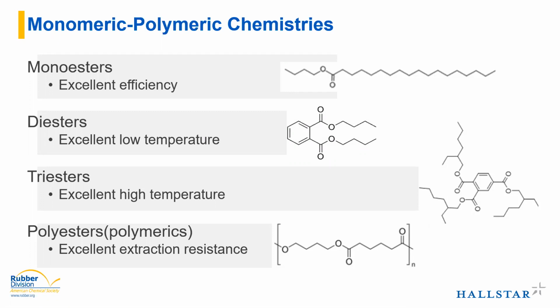Triesters are also still fairly widely used. The one shown here is TOTM, trioctyl trimellitate. These have 3 ester groups coming off of a central, usually aromatic ring for something like a trimellitate. They offer excellent high temperature performance, especially for a monomeric, which typically aren't as strong in high temperature applications. Triesters really do a good job in that area. Polymerics, polyesters can vary so widely that it's really difficult to group them into any further groups. So we really just leave them as polymerics, polyesters. And what they mostly offer is excellent extraction and migration resistance because they are so large.